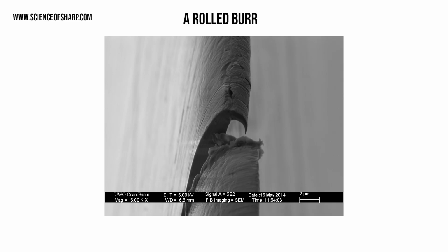I did mention earlier that I would explain how I think sometimes you can actually recover tooth by stropping, so I'll explain that now. My theory is that this class 4 burr has rolled or deformed, and that you are realigning and abrading it back into shape. However, this does not require a 6 to 15 micron or a 20 micron compound to achieve. More abrasion means more burr removal, which means less tooth. So if anything, the plastic deformation which happens from the force of the substrate pushing the burr back to stand up is recovering the tooth.